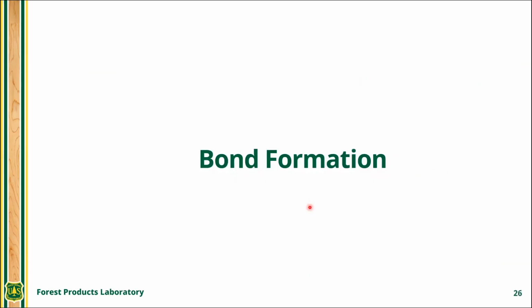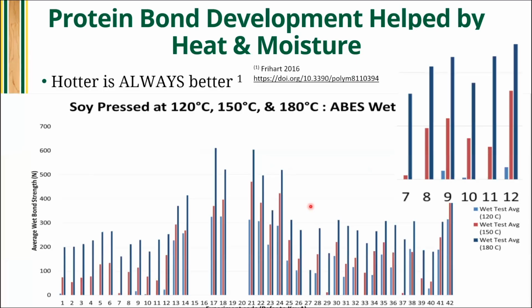Okay, bond formation. Heat is really helpful for protein bond formation. Here we had 42 different soy, and I think maybe we also had some canola in here as well, but all kinds of permutations of the recipe. And for each one of these materials, 42 different materials, I blew up just a few of them so you can actually see. Material number 9, this blue line here, the ABES specimen was made and pressed for 2 minutes at 120 degrees C and then tested wet.